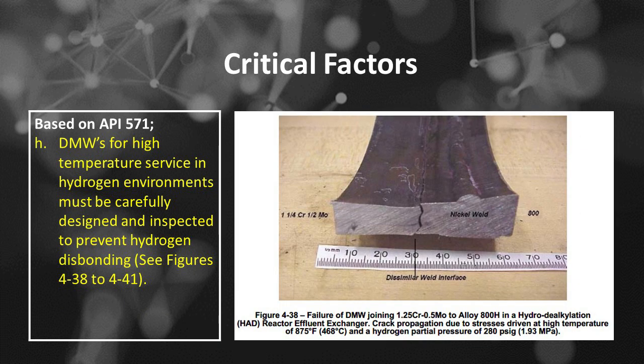The eighth is dissimilar metal welds for high temperature service in hydrogen environments must be carefully designed and inspected to prevent hydrogen disbonding. See Figure 4:38. Failure of dissimilar metal welds joining 1.25 Cr 0.5 Mo to alloy 800H in a hydrodealkylation, or HAD, reactor effluent exchanger. Crack propagation due to stresses driven at a high temperature of 875 degrees Fahrenheit, or 468 degrees Celsius, and a hydrogen partial pressure of 280 psig, or 1.93 MPa.